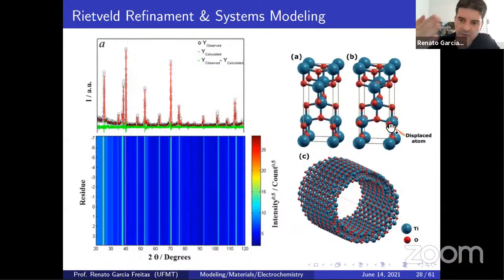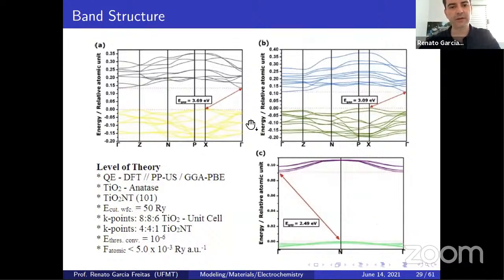So we put a vector, let's say here, to displace this oxygen, and we have this model here, perfect titanium oxide, disordered oxygen, and we simulate a titanium oxide nanotube properly. So we have a band structure here with an indirect band gap of almost 3.6, indirect, from X to gamma. For the perfect one, as soon as we increase the shift of the oxygen position, we decrease the band gap values, the valence band and the conduction band, 3.09 down there, indirect band gap as well, gamma C.